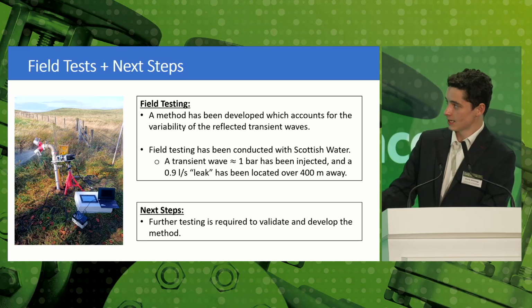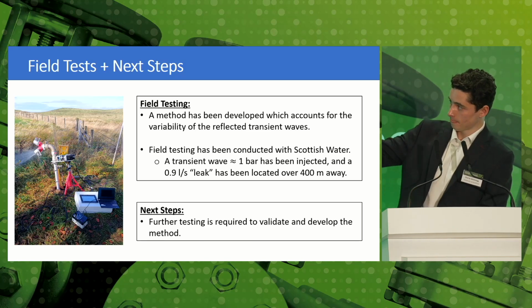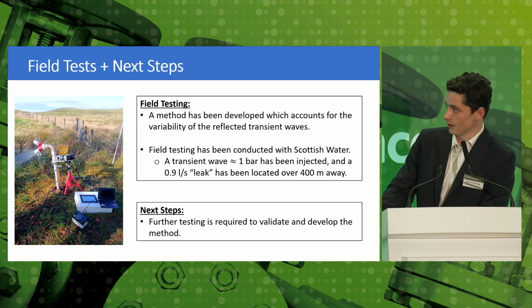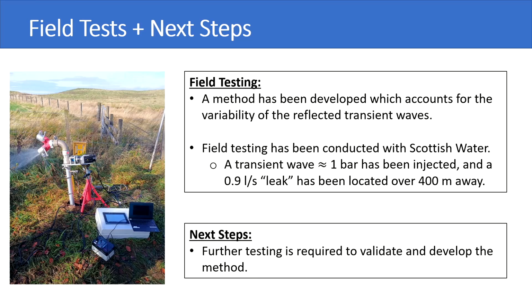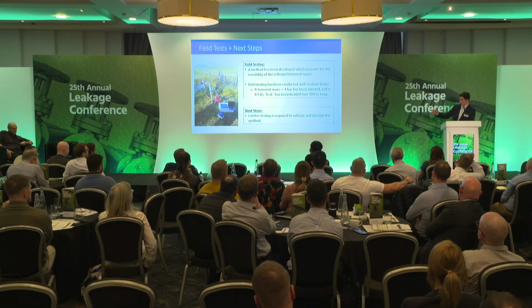And we've taken that and applied it in the field with Scottish Water. And there's a nice picture on the left of the field setup that we've got. And the early results are quite promising. We injected a transient wave of 1 bar to ensure that we were below the threshold of the pressure rating of the pipeline. And we simulated a leak over 400 meters away on another hydrant by opening it slightly. And through that, we've been able to pinpoint that leak location.